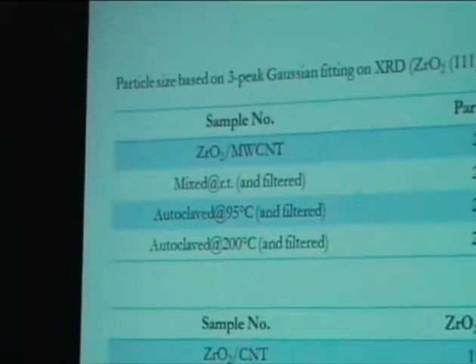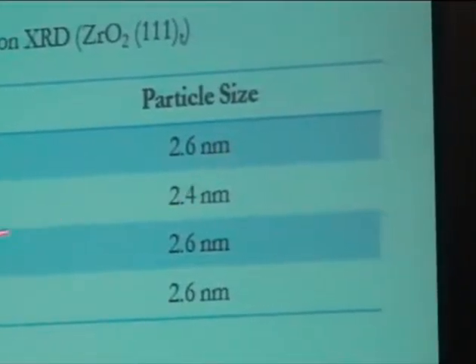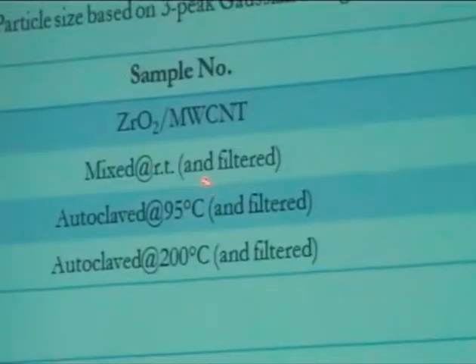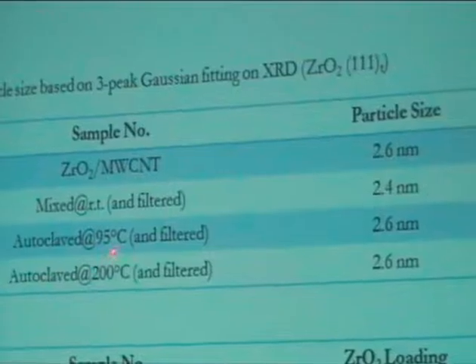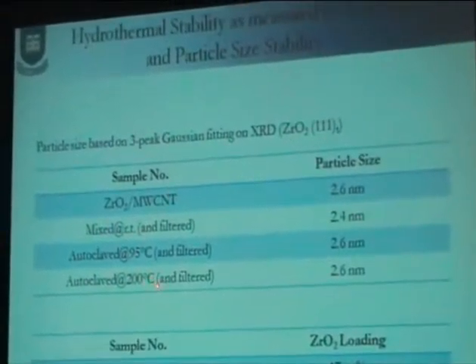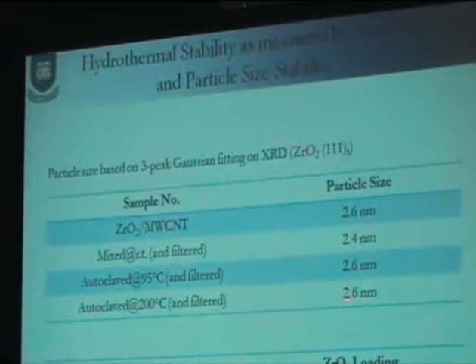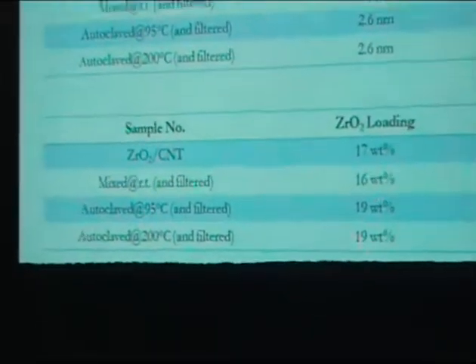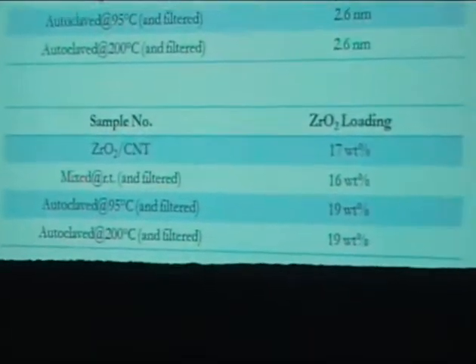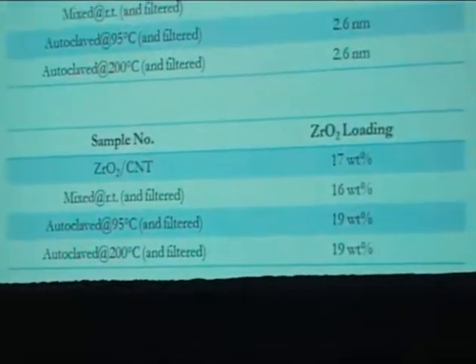So I'm going to quickly, this is about the charge transfer, it's not about the catalysis, but of course you will want to be reassured that this has some relevance, and I'm going to try to give you just two bits of relevance. One is that the small particles of zirconia are not only thermally stable, they're hydrothermally stable, because here we started out with 2.6 nanometer particles. We heated it for 6 hours at room temperature, 6 hours at 95, and 6 hours at 200 degrees Celsius. And essentially the particle size doesn't change, and if we measure the loading within experimental error, we're not dissolving or removing any zirconia, so they're quite stable.